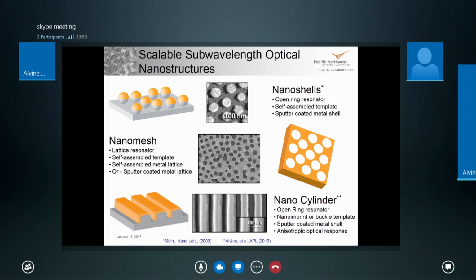If you take a cross section perpendicular to the lines, in all of these, the bright regions are metal and the dark regions are dielectric. So when you look across the line, you get this nanoplasmonic resonant response. But when you look along the direction of the line, you're essentially seeing an infinite metal surface, and so you get a very strong polarization dependence.